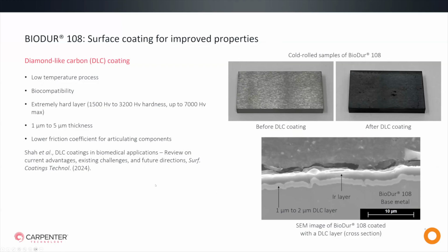In addition to nitriding, BioDur 108 is also compatible with surface coating technologies. So we did confirm in part of the patent that DLC, or the diamond-like coating, is compatible and they do not degrade the matrix. Now the thickness is a little bit thinner, right? But they can provide an extremely hard surface beyond what can even be measured on the Rockwell scale. Again, it can provide some low friction coefficient options, great for articulating components, and the biocompatibility of this particular coating has records and acceptable clinical use.